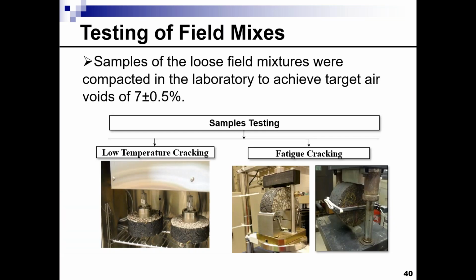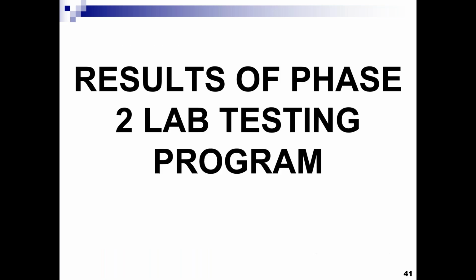So for the mixes that we had, we obtained samples. Because we had a lot of test sections, the main focus was on fatigue cracking and low temperature cracking, basically the cracking resistance of those mixes. All those mixes were compacted at the target air void of 7 plus or minus 0.5, and they were tested in the lab.